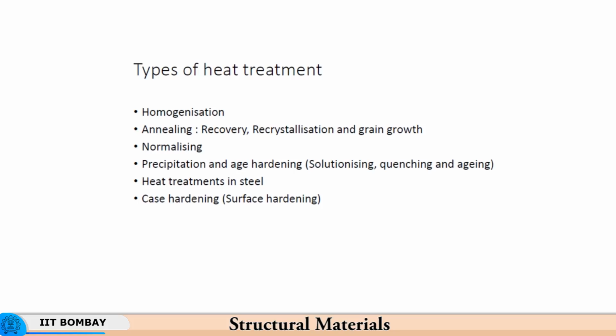So, the first treatment that is given is homogenization, because there is a possibility that during the course of previous processing there would have been so-called segregation, or non-uniform distribution of elements in the material. Now, this is typically so when the previous step has been a casting process. For example, if you have just poured hot metal into a mold, and by the time it solidifies, you have different phases formed there, but during the course of solidification you do not have uniform distribution of alloying elements everywhere.